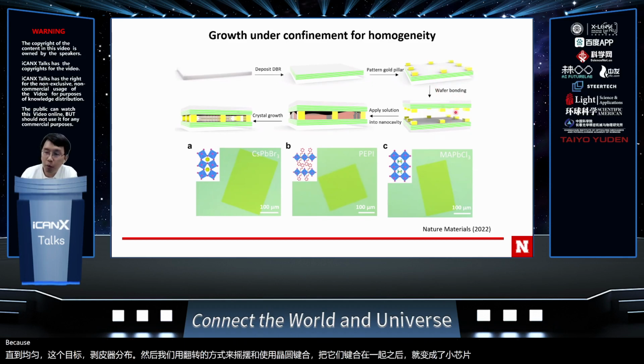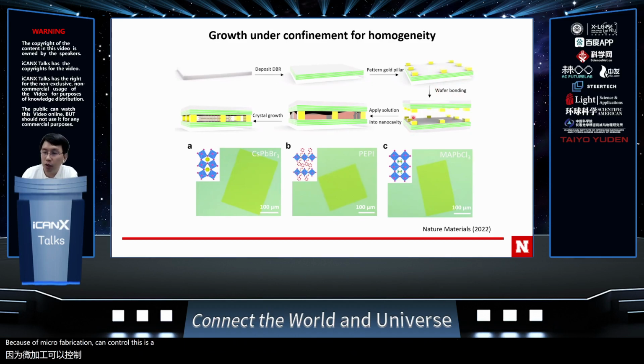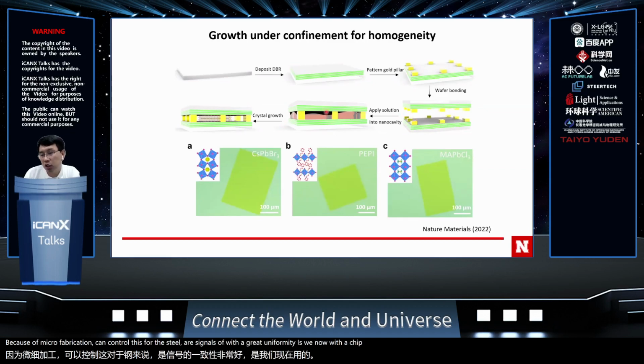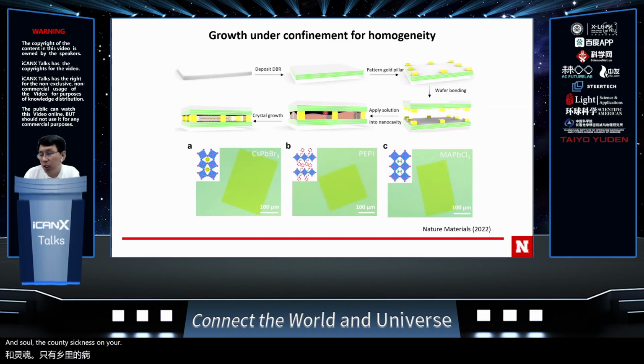Because microfabrication can control the gold pillar thickness with great uniformity, a chip can show cavity thickness variation of only about 1 or 2 nanometers over a small scale, which is pretty ideal. Then we apply solution into the cavity and let the crystal grow directly inside. Afterwards, we get very big crystals. As you can see, the method is also general towards multiple materials with an excitonic component. The optical imaging shows homogeneous properties along the thickness.